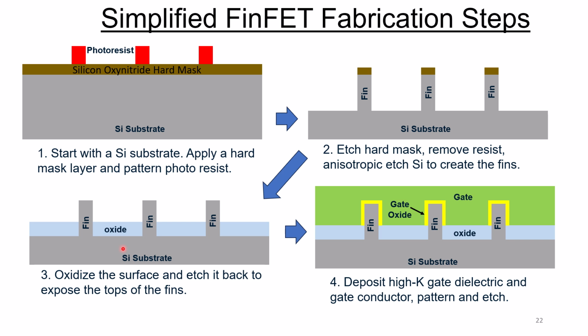Now I'd like to go over a series of simplified FinFET fabrication steps. We're skipping hundreds of steps here just to show you the very basics of how the FinFETs are fabricated. So what we're going to do is start with a silicon substrate, and we're going to apply a hard mask. And this hard mask is possibly nitride, or maybe it's silicon oxynitride. Now you put photoresist on it, and you define the photoresist in the pattern that you want. Next, you move over here and you go ahead and etch the hard mask away.